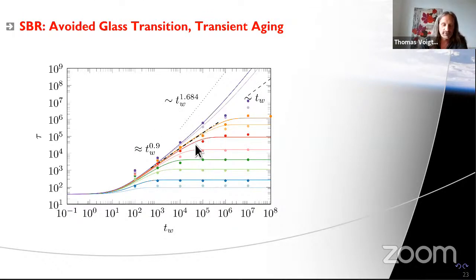I took data from simulations of you guys. We had the fit with schematic mode coupling theory, which of course predicts an ideal glass transition. It predicts this hyper-aging regime. And now I'm saying, yeah, but here with these two points, I should really acknowledge that if I quench into the glass, there might not be an ideal glass. So I need to include not only mode coupling theory, but the stochastic version of it.